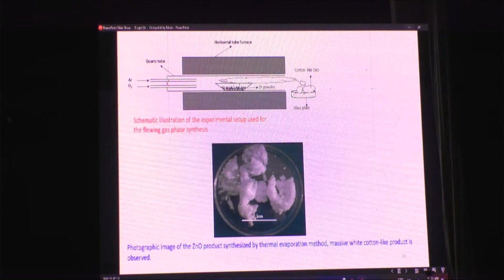As I told you, we made our own hand-designed furnaces. In this furnace we use argon as a carrier gas and oxygen as a reactive gas, with a high carrier flow rate. Basically, we found different structures at 100 SCCM, 200 SCCM, 400 SCCM and so on.